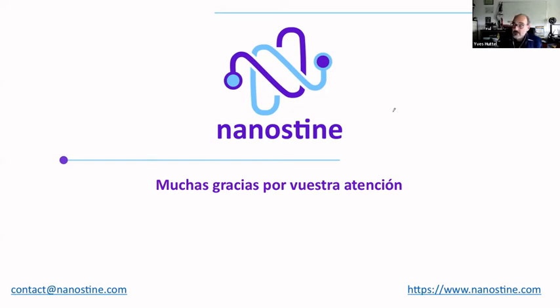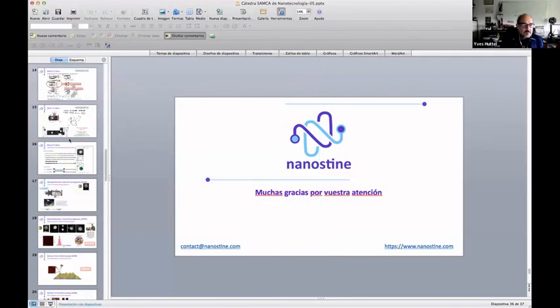And what we found is that when you make gold nanoparticles and you inject a teeny quantity of water vapor, the water vapor sticks on the surface of the nanoparticles, and this allows you to form what we call satellite structures. I will show you that. Let me find the slide. As I have shown this in the TEM images. Yes, this one.